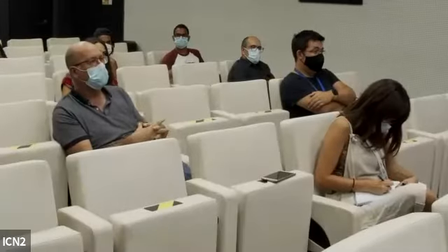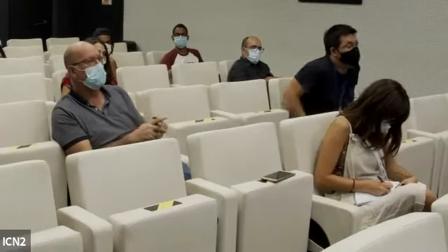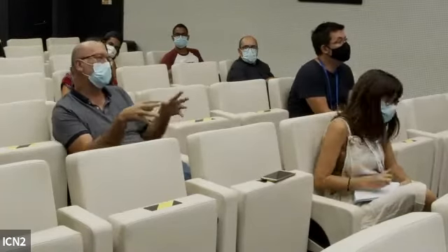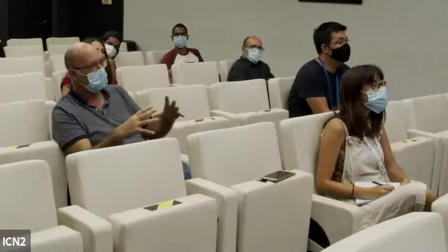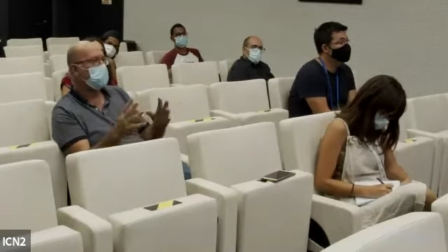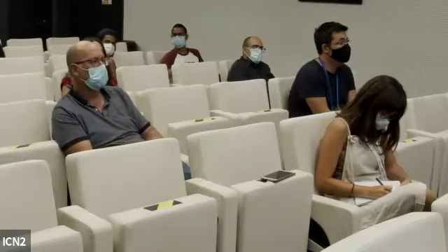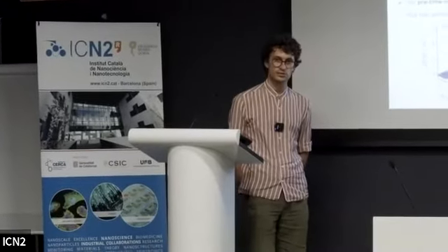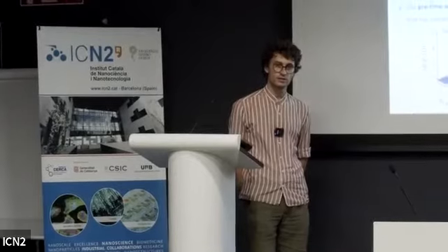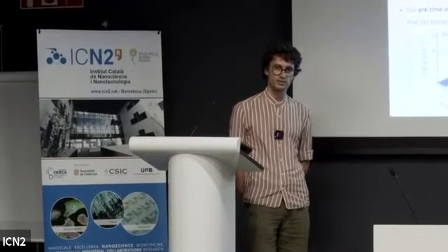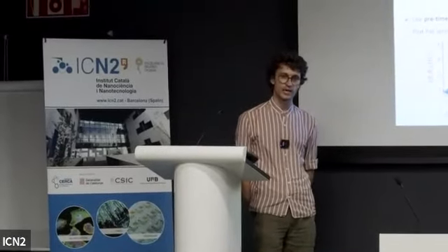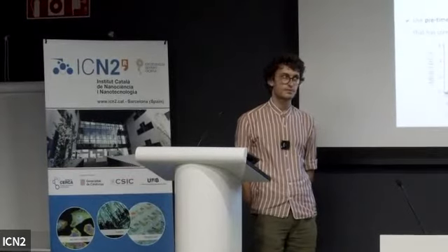Yeah. So what is the time scale of the measurement? In the one that you showed that you have a temperature increment of 10K, that was done on the femtosecond regime, or it was microsecond regime? My question is, if this is related to the electronic temperature, or this is just the lattice vibration temperature, or if you can decouple both, and how that works in this technique. This would be the lattice temperature. So the electronic temperature would be initially much higher, but then that energy relaxes and transfers to the lattice. So the lattice is 10 Kelvin higher.